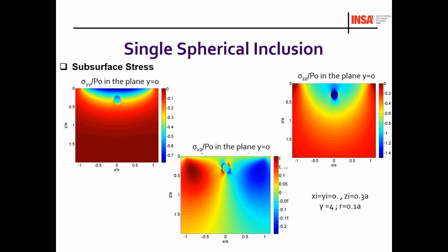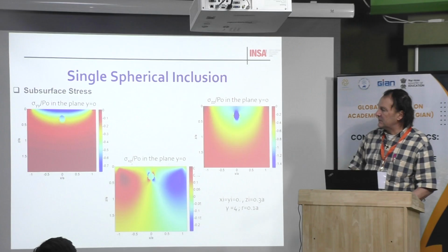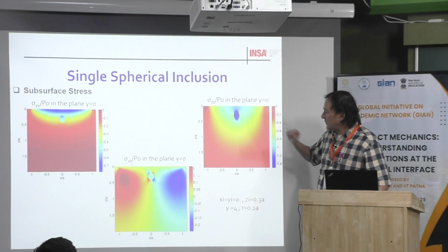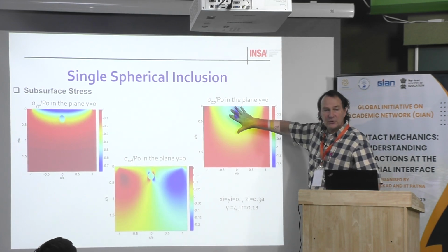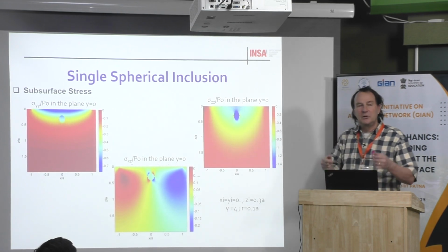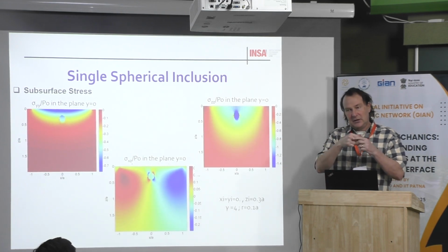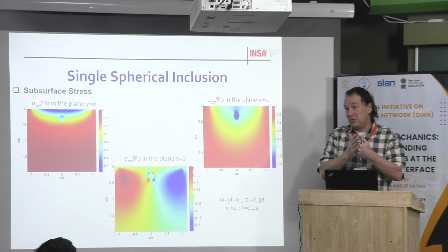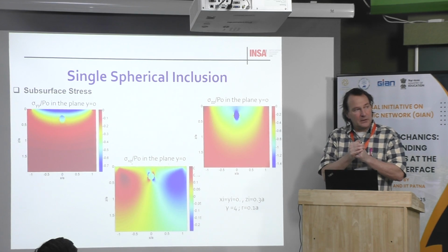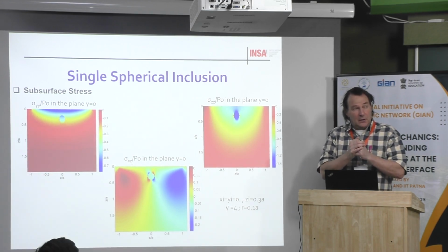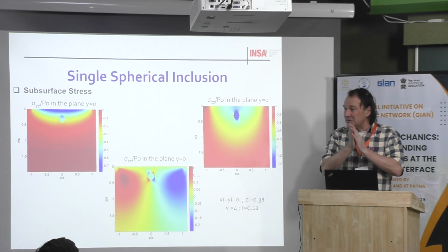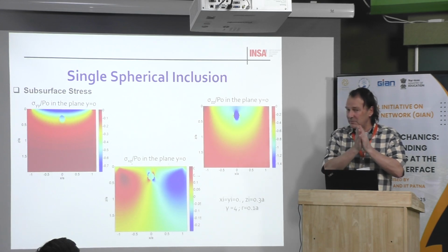Although we are able to calculate the different stress within the material, what will be interesting here is to calculate the stress around the inclusion, at the boundary between the inclusion and the matrix. Why? Because, for example, if you calculate the shear stress, maybe you can know if the two surfaces may be sliding, for example. If you have no cohesion, then you can have something like that.